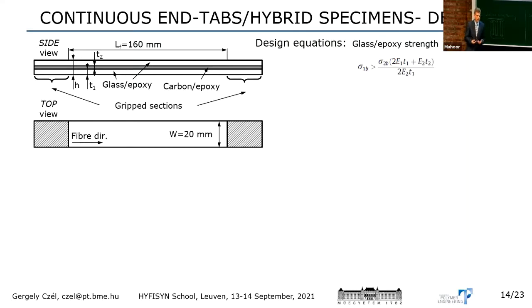But it's hard to make sure which layer we had the initiation of the final failure. So it's best to keep the glass layer intact, because in this case we can make sure that it was the carbon layer which initiated final fracture. So that is the simple equation to make sure. And these are just the elastic moduli of the layers and the strengths of the carbon layer and the layer thicknesses. Nothing really complicated.